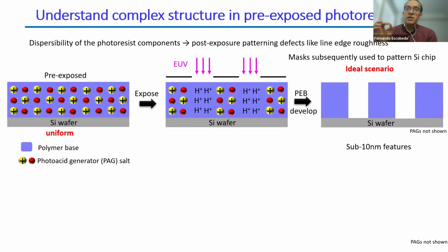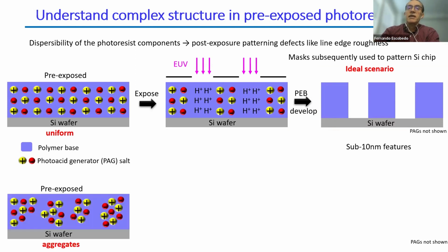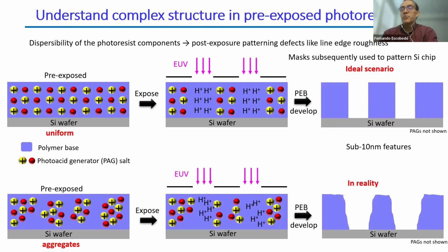But the idea is that we want to make these features very small, sub 10 nanometers. The problem is that for a long time, it has been recognized that these PAGs, which are really ionic salts, are likely not that uniformly dispersed in the material, but more likely have some degree of clustering. There was some experimental evidence that this is the case. And if you were to follow the same process, then at the end, your patterns will have this sort of edge roughness that can be very significant.